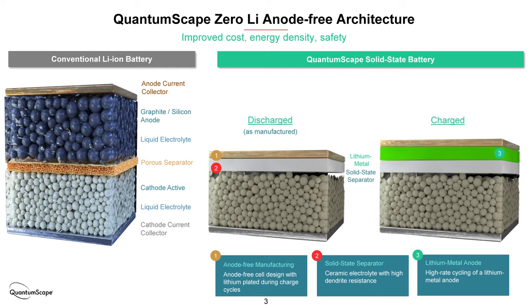So by eliminating that anode layer, you eliminate the volume and the mass of the anode, you gain the energy density benefits of our approach. You also get the benefit of increased power density, because one of the bottlenecks to fast charge in today's chemistries is the time it takes for lithium ions to diffuse into those carbon particles. So if you eliminate the carbon particles, you eliminate that bottleneck, and now you can charge the cells as fast as the cathode can deliver electrons to ions, which is 15 minutes, right?